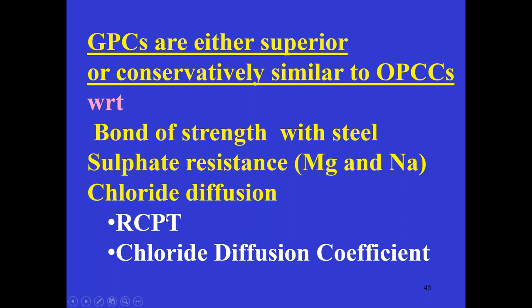And regarding chloride diffusion, this study we made a lot, and RCPT is not designed for chloride diffusion. Never. It was designed only for OPC concrete, not for any other concrete. It was not designed for fly ash concrete, not designed for slag concrete, never. So this number, what they give, ASTM, is not valid because we never measure chloride content here. That's why it is not a good parameter for measuring the chloride diffusion in real terms.